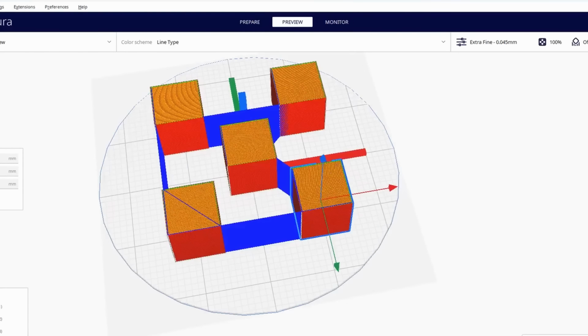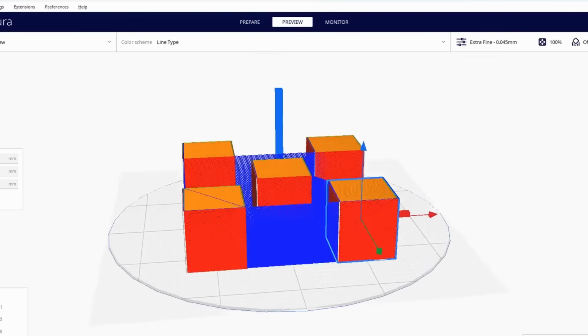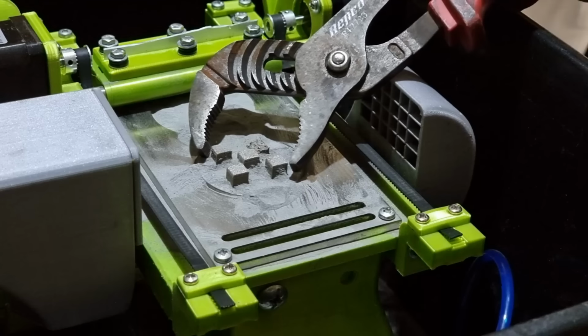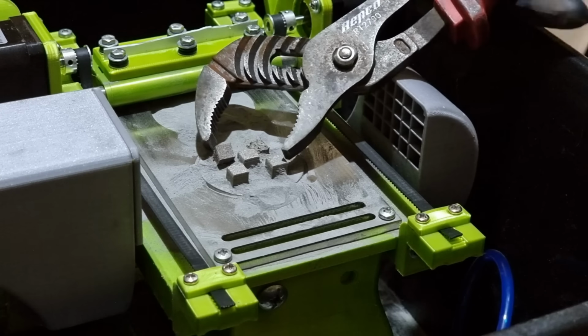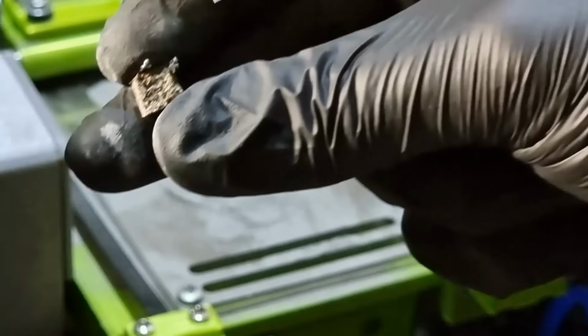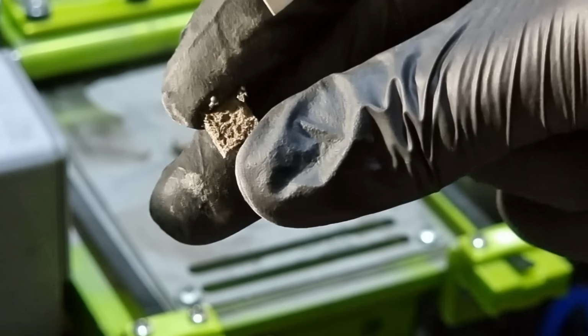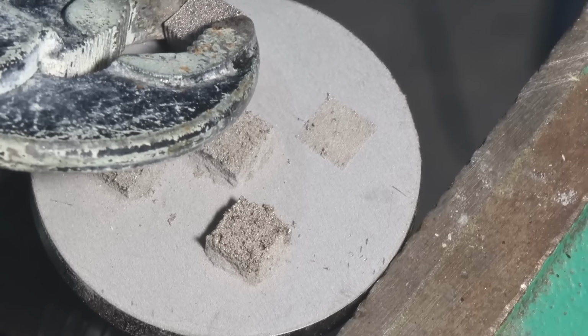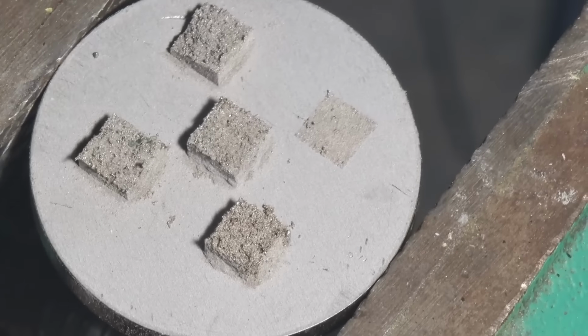I followed this up with a few more tests, mainly driven by the curiosity of what faster speeds could yield. The next run would consist of 5 cubes ranging from 400 to 800mm per second, with wall speeds the same and a hatch spacing of 75 micrometers. Before I could get them in front of a sandblaster, immediately it was apparent that a laser fusion would see these settings as not much more than a candidate for support material. And with my very formal method of testing, not one of them would survive.